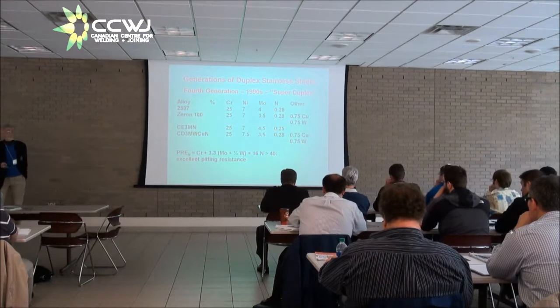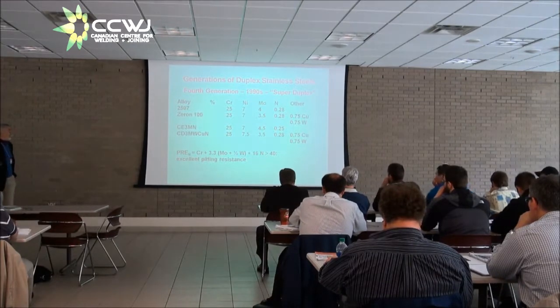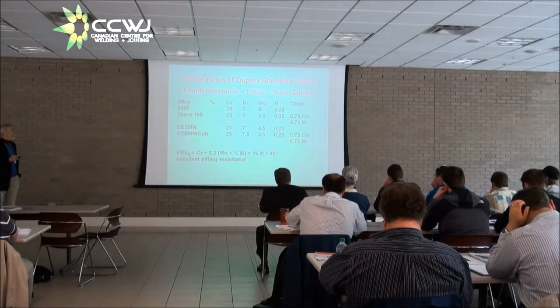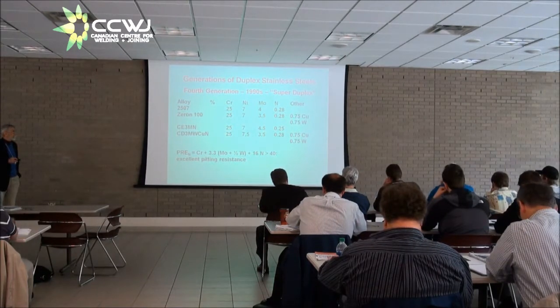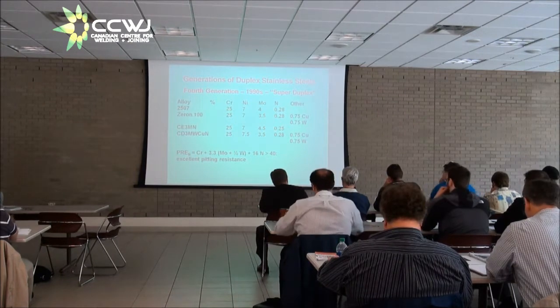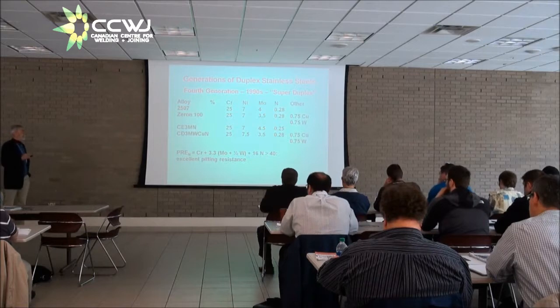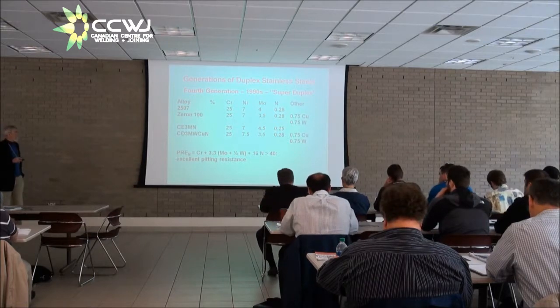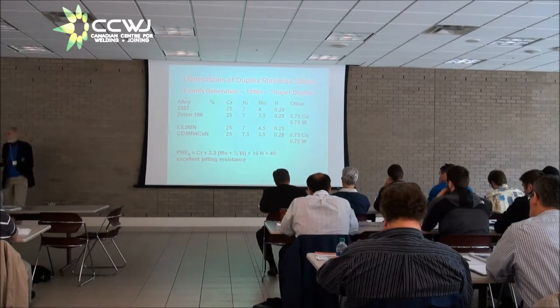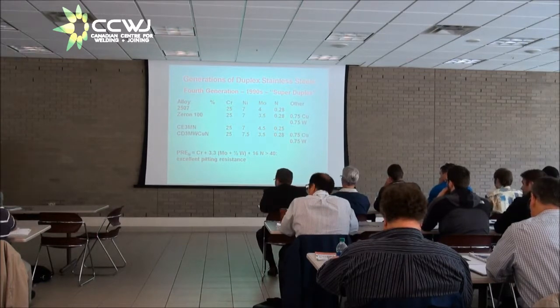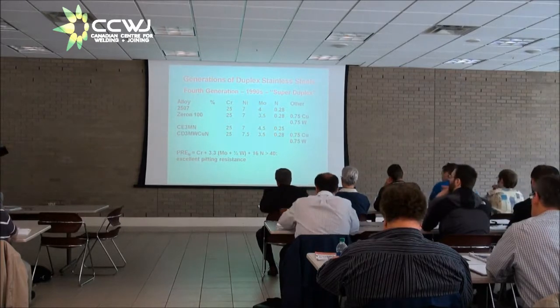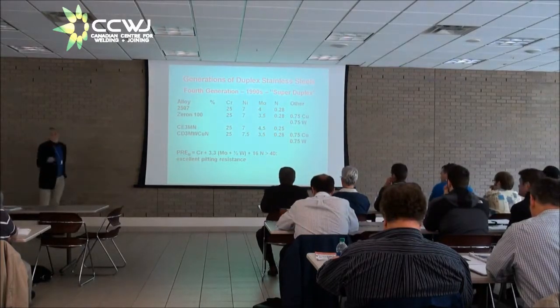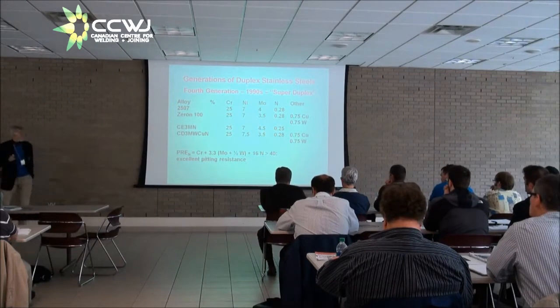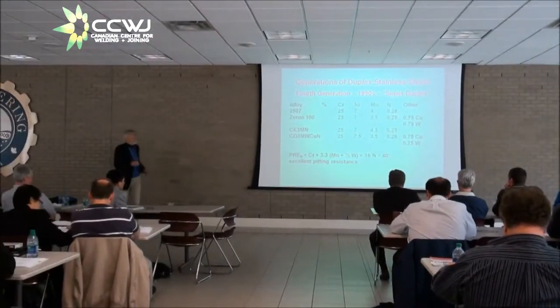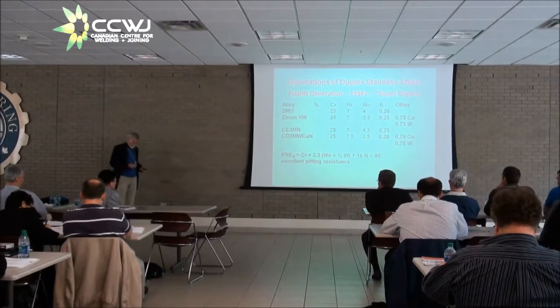And these are the so-called super duplexes. There are two main alloys in the rod form, 2507 and Zeron 100. And here you can see Zeron 100 contains an addition of tungsten, which gets its pitting resistance index up over 40. And then the cast version, CD3MN, is the cast version of 2507, and CD3MWCuN, that's a mouthful, is the cast equivalent for Zeron 100, respectively. So that's your fourth generation of duplex stainless steels.